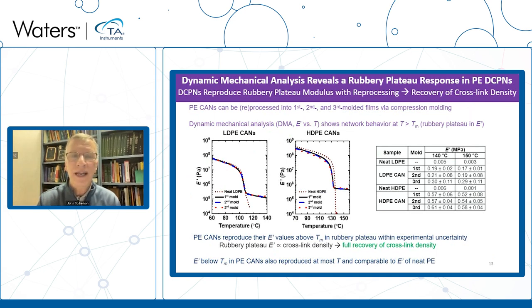These materials, again, we can actually characterize in terms of cross-link density in these particular cases. And here we illustrate the excellent reproduction associated with these systems. We also show the case of the neat low-density polyethylene and the neat high-density polyethylene, which don't exhibit any rubbery plateau modulus, and that's because the materials are not cross-linked. Once they go through their melt transition, they actually just flow. But the cross-linked materials that are dynamically cross-linked actually show the rubbery plateau. And as a function of reprocessing in these cases, we get excellent reproduction associated with the modulus.